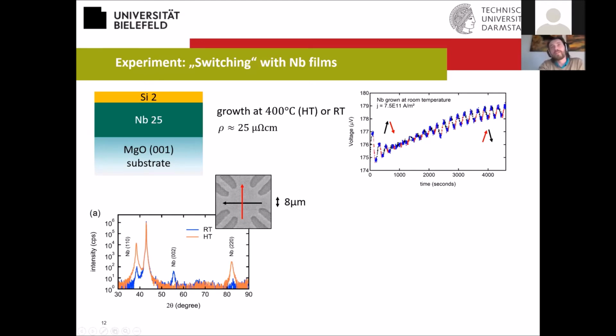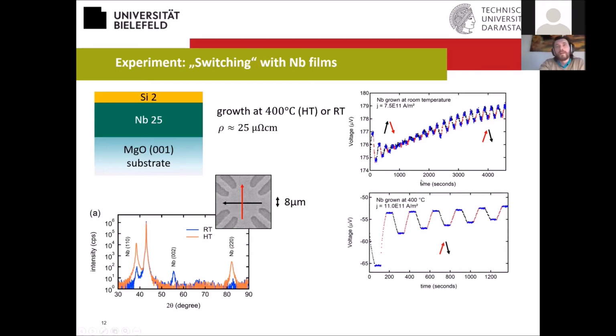But something odd happens in this experiment. After a couple of cycles, this response vanishes, and then it seems to come back. But when you look closely, you see that the sign has changed. Here we have black and then red, so pulsing along this direction, then pulsing along this direction, gives up, down. And then later, this gives you down, up. So apparently the sign of our apparent switching changes here. Then we also did the same experiment with niobium grown at 400 degrees C, so with this high temperature epitaxial sample, and we see that it just goes up, down, up, down, up, down, without any sign changes, no matter what we do with the current density. So you can ask yourself the question, what is going on here? Where does this signal come from?